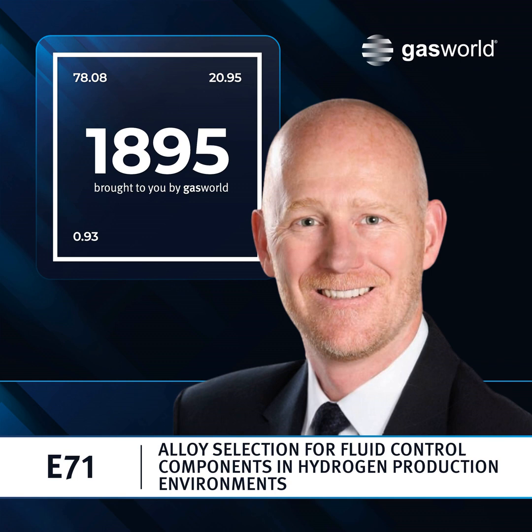Those higher pressures, on the order of hundreds or even 1,000 bar, now create enough stresses in the material to bring hydrogen-assisted fatigue or hydrogen embrittlement into the picture. And so at this point, a very well-designed component that is made for hydrogen service out of a high-quality 316 austenitic stainless steel is a very cost-effective solution.